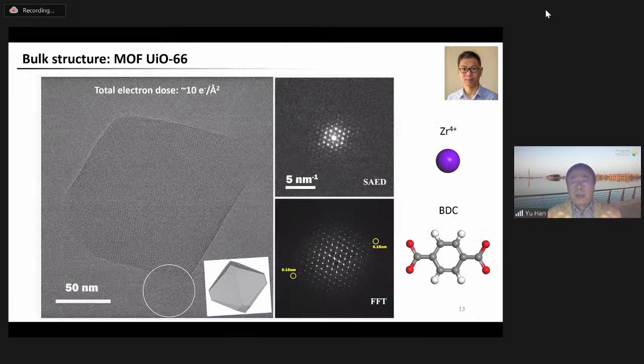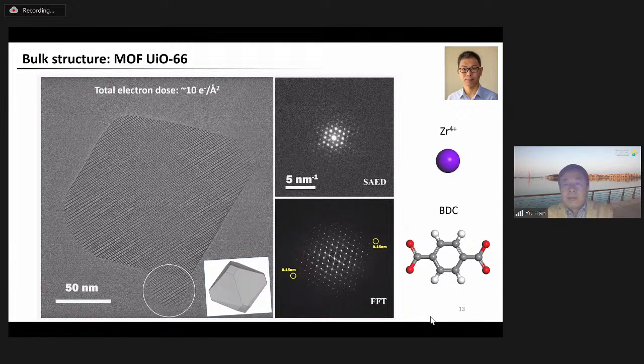Before studying local structures, we started with the bulk structures. Most MOFs have known crystal structures that are solved by single crystal X-ray diffraction. So in this sense, imaging the bulk structure doesn't provide additional structure information, right? However, imaging the known bulk structure is necessary and actually very important. This is because the known structure can be used as a reference, which allows us to confirm that the imaging conditions used are safe enough to preserve the structure from damage.